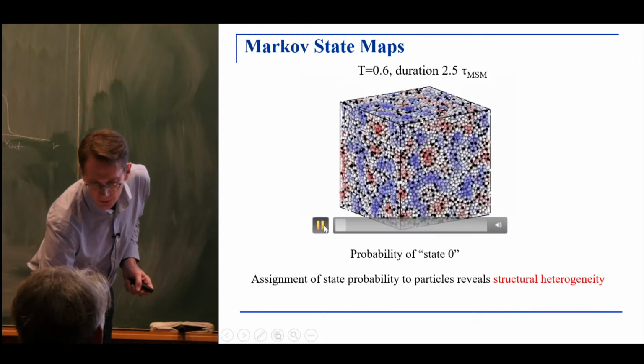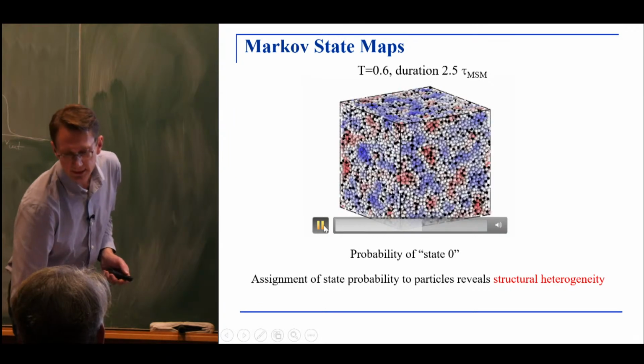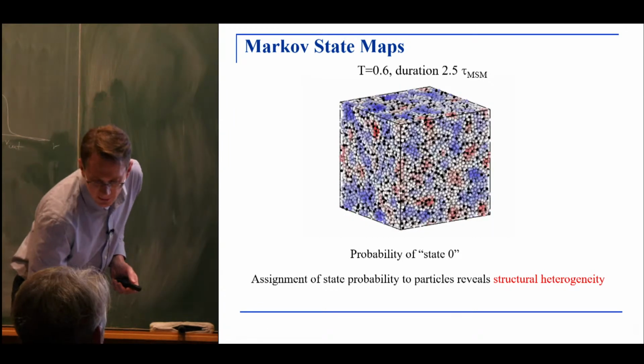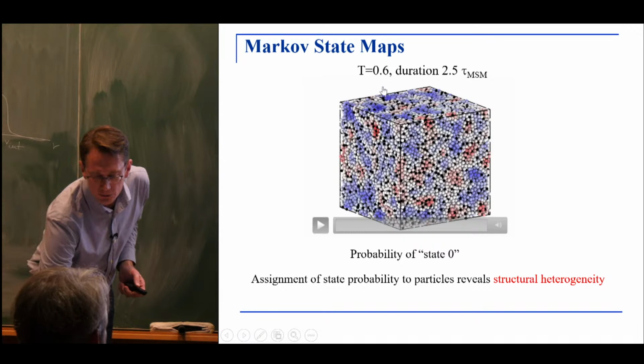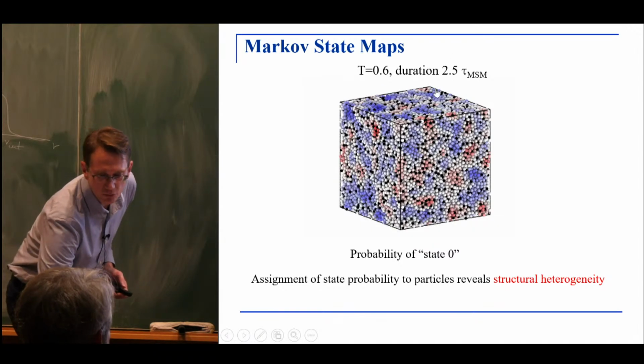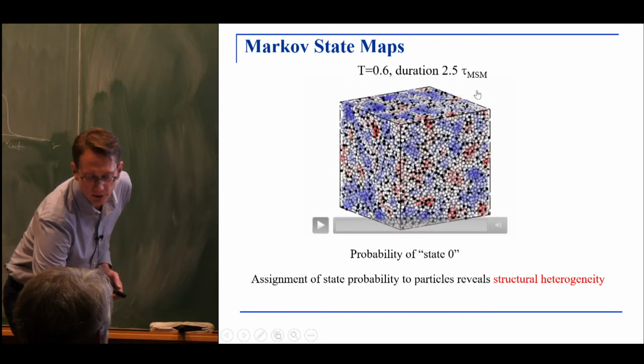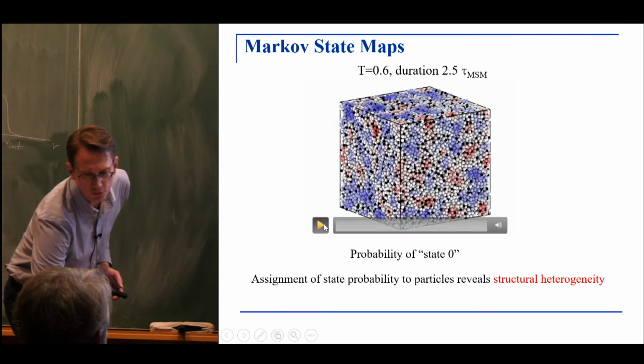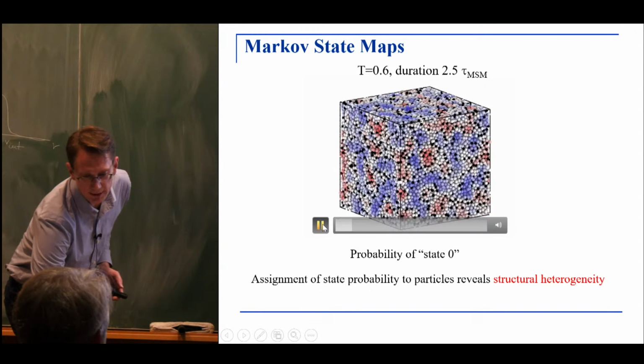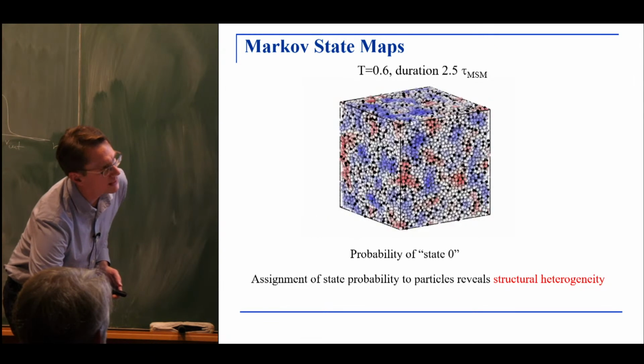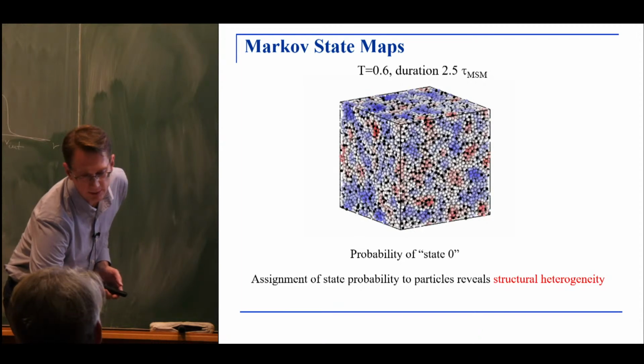And what you can see is the flickering. The duration of this movie is about 2.5 times the Markov state model time. And that is certainly enough for this map to decorrelate. So if you focus your eye on one of the blue or red clusters, you will see that they melt away in the course of the simulation, right?